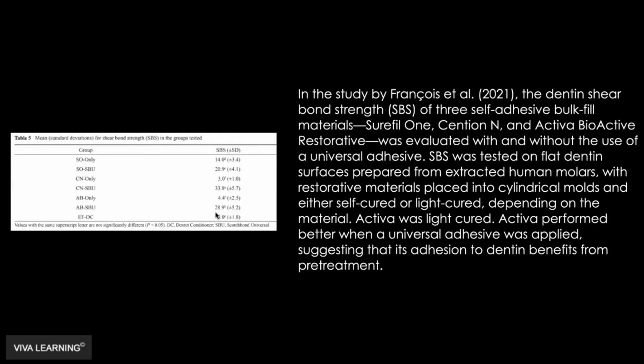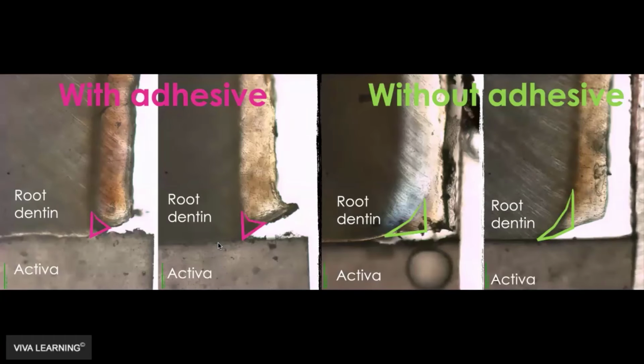Your next question would be, if I use a bonding agent, can this still be bioactive? Can you still get ions that come out of that Activa material to help remineralize the tooth structure? Well, Chanta did all this work. I just helped him. When Chanta did this work, he had some specimens where he applied bonding agent in his preps and some where he didn't. When he did not apply bonding agent, he saw wall lesions, where there's more demineralization next to the restorative material. In comparison, when he used an adhesive, he actually saw a slight zone of protection, where there's less demineralization next to the restorative material. So Activa does better with the bonding agent as far as bond strength and even with its bioactivity, or prevention of demineralization.